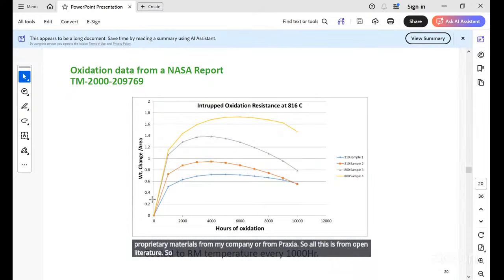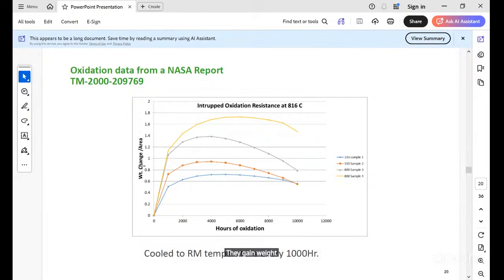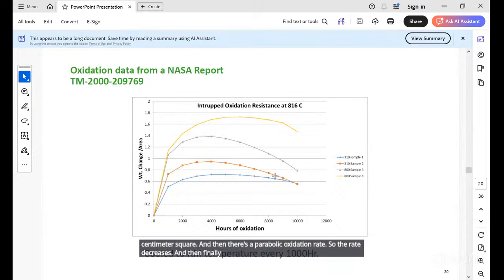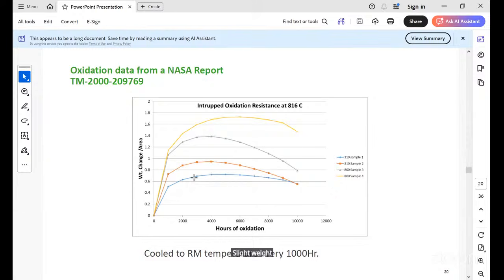So it is showing that these alloys, 310 stainless steel and 800 alloy, gain weight, very little weight. That weight change is in milligrams per centimeter square. And then there's a parabolic oxidation rate, so the rate decreases, and then finally the oxide scale cracks, falls off after thousands of hours and starts losing weight. So you want to have slight weight gain, but not start losing weight. So that's the very standard method of testing.